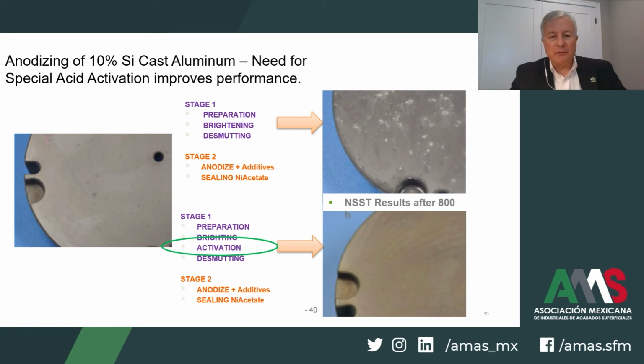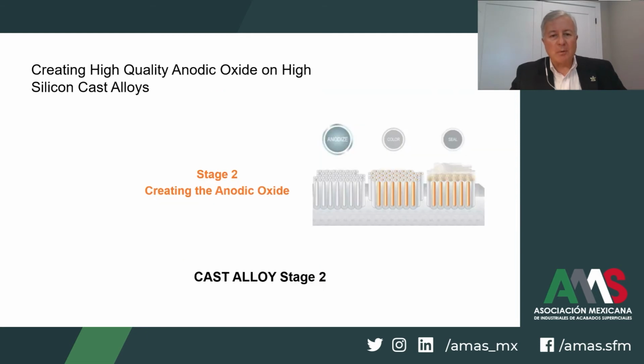In the bottom right photo example, the important incorporation of the special acid activation step manages the negative impact on the silicon and on the surface, and the result here is that there's no corrosion after 800 hours of neutral salt spray. That's why we say that stage 1 and stage 2 considerations are very important. For stage 2, once the proper preparation considerations are implemented, the creation of the anodic oxide takes place with improved efficiency. So let's talk about some of these details.